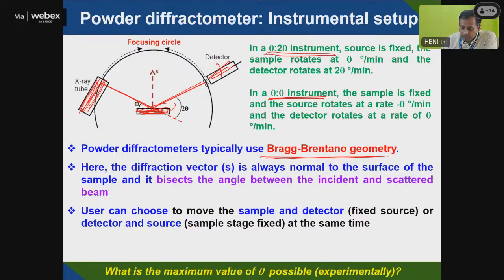Here, the diffraction vector is always normal to the sample surface and bisects the angle between the source and the detector. This is the focusing circle. So the user can choose to move the sample and detector with the source fixed, or the detector and source with the sample stage fixed. So what is the maximum theta possible experimentally? You can see the detector is moving by theta and the source is also moving by theta. The maximum angle, if you take it to here, is 90 degrees. Beyond that it's not possible.